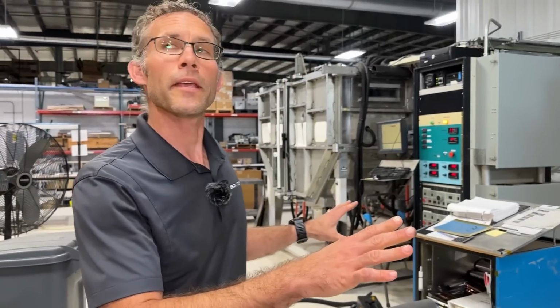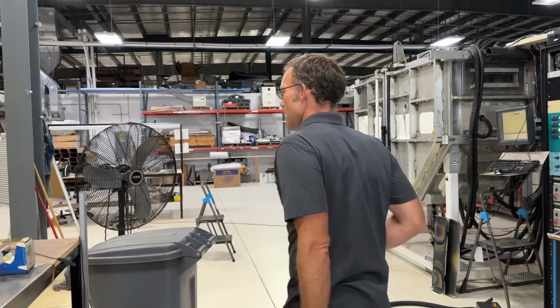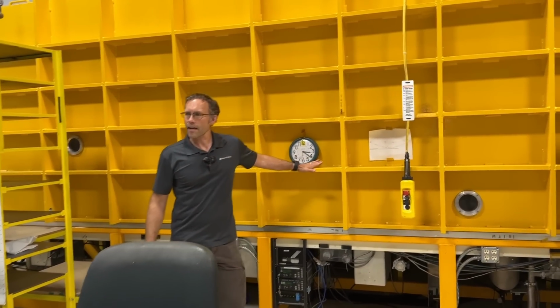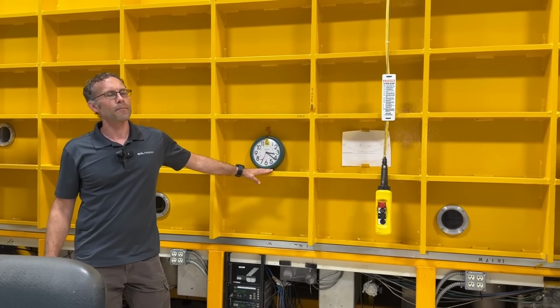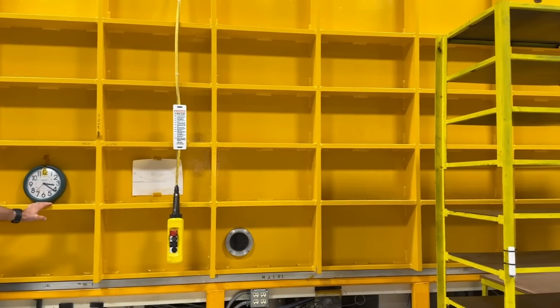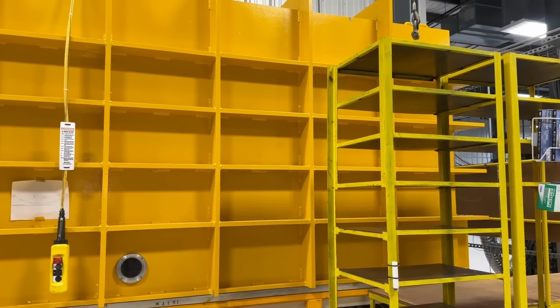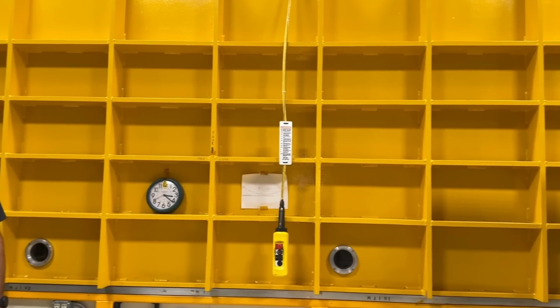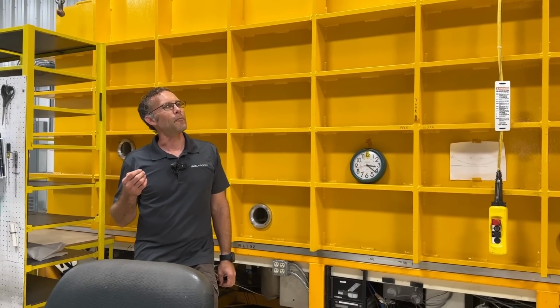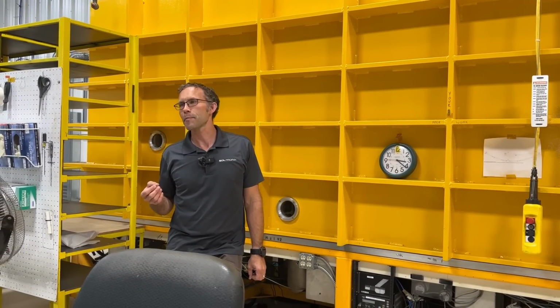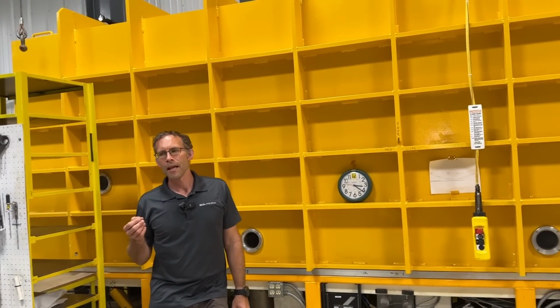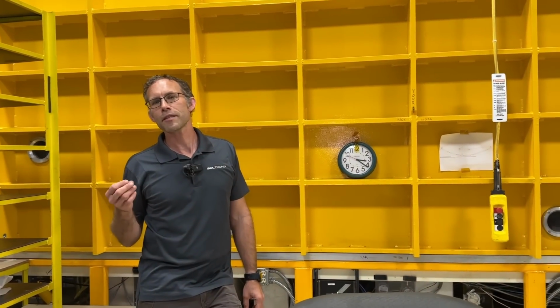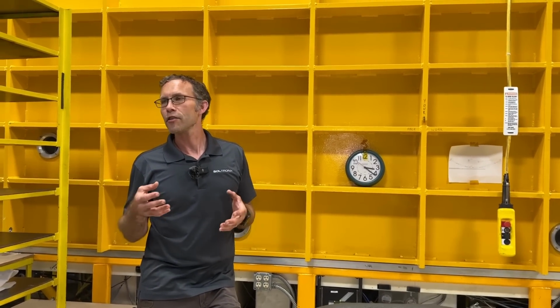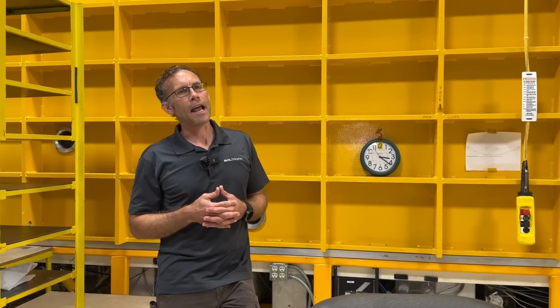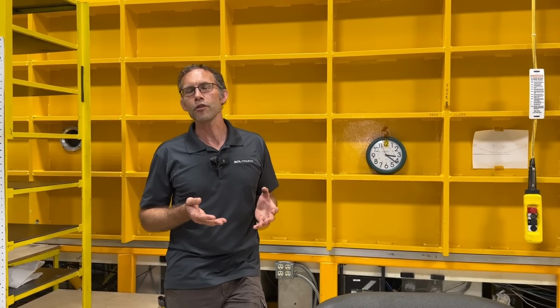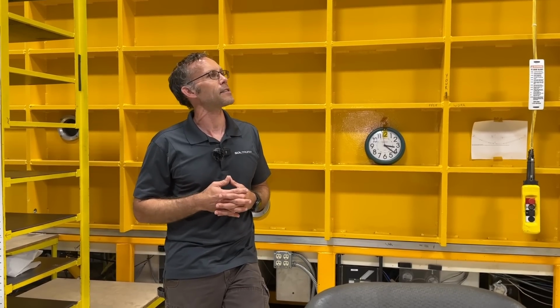Okay, so from here, we're gonna switch gears and go over to these guys. These are our amorphous silicon machines. Most of the amorphous silicon we make is a tandem amorphous silicon. The reason we use a tandem cell is because amorphous silicon suffers from an effect called Staebler-Wronski, which is basically a light-induced degradation. You'll see it happen over the first 100 hours of panel use in light, and then it pretty much stabilizes.